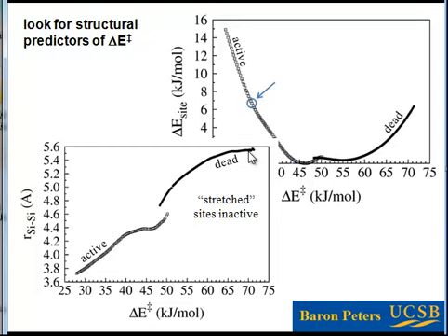But you can definitely see that it predicts that as you go to very, very high activation energy sites, those are the dead ones, the distance between the two silicon anchors to the amorphous support is getting farther and farther apart, right? So it appears that stretched sites are less active than sites where the anchors have been pushed together. And so that's an interesting result. It's sort of something that might tell you something about where your dominant source of reactivity is coming from.